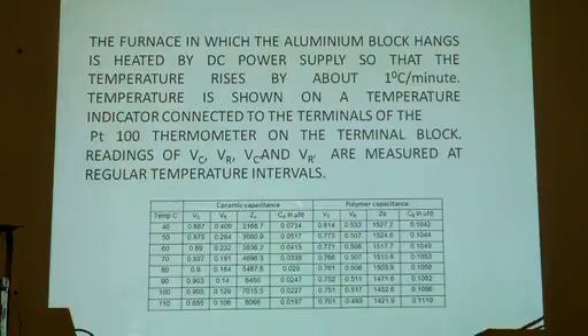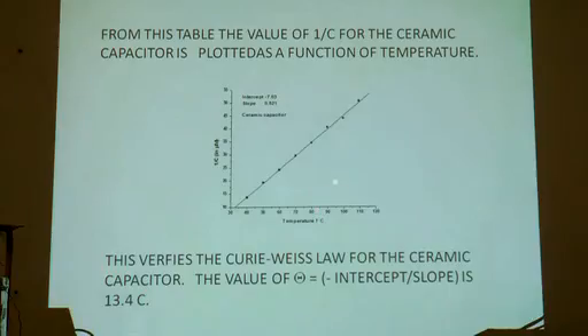From this capacitance, I calculate the reciprocal 1 by C and I plot 1 by C against the temperature T. You see it is a straight line. The intercept is minus 7 and the slope is 0.521. The straight line shows that the Curie Weiss law is obeyed, and if you divide minus intercept, that means plus 7.03 by 0.521, that is 13.4, that is the Curie temperature theta. So, we verify the Curie Weiss law for the ceramic capacitor and its Curie temperature is 13.4 degrees centigrade.